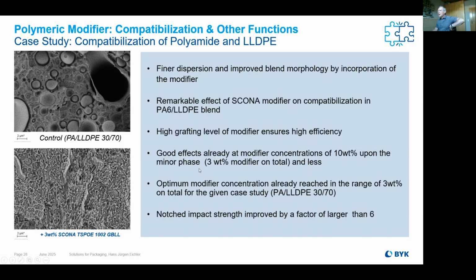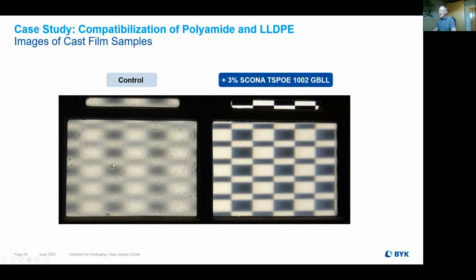So what we found out during our experience is that the optimum modifier concentration is already reached in the region of 3%. Especially here for the mixture of 30-70, the notched impact was increased by a factor of 6. That's really a lot. Besides these mechanical properties, we also checked the film, and what you see is the control is really bad. You see a lot of spots inside, so there is no chance to look through the film. And with 3% of the Skona modifier, you have a really clear film and nice dispersion of the matrix. So with this, you can work and play around and run some nice film samples again.